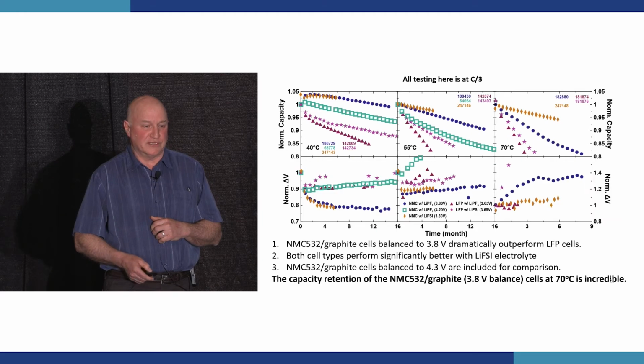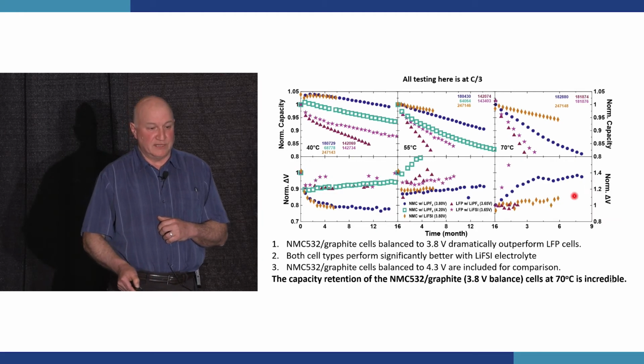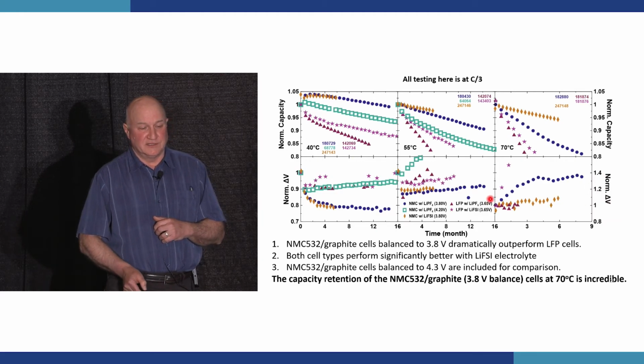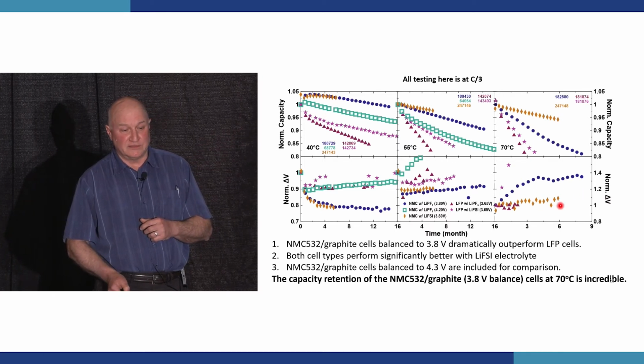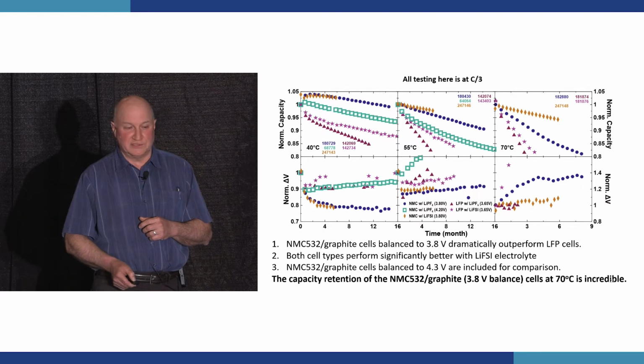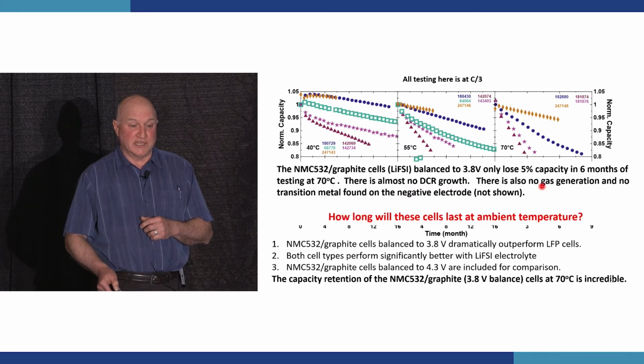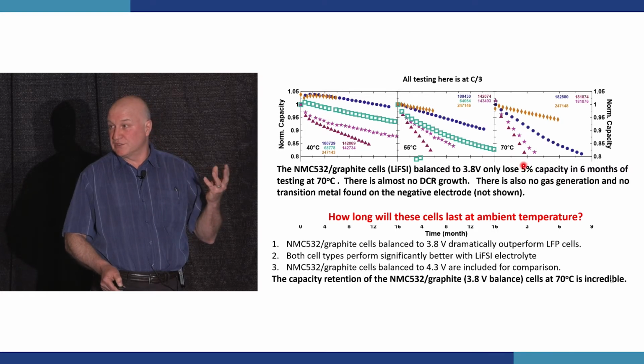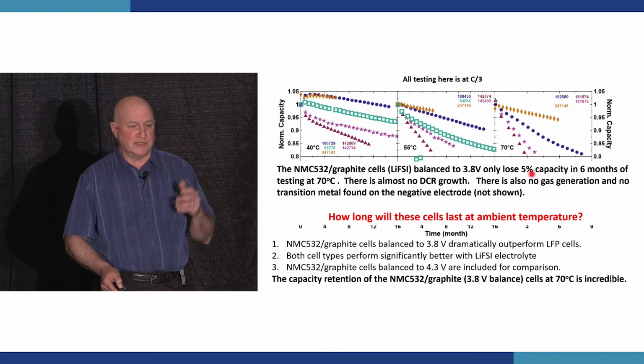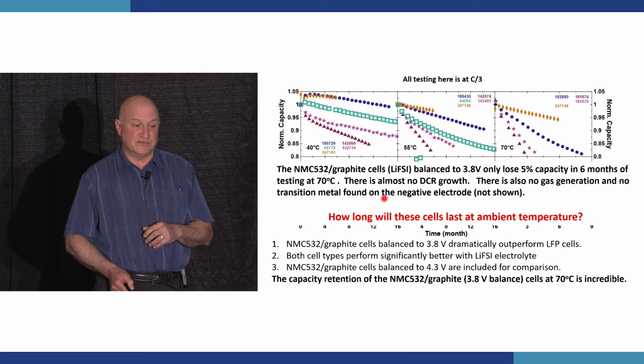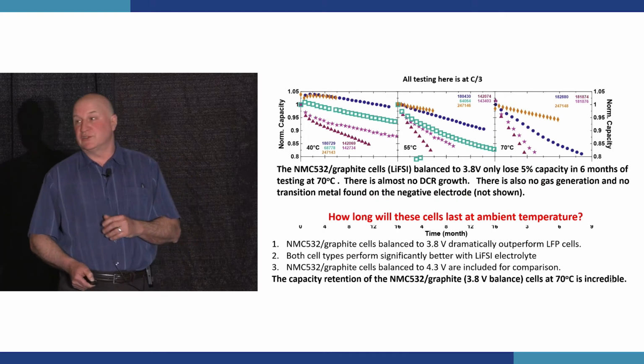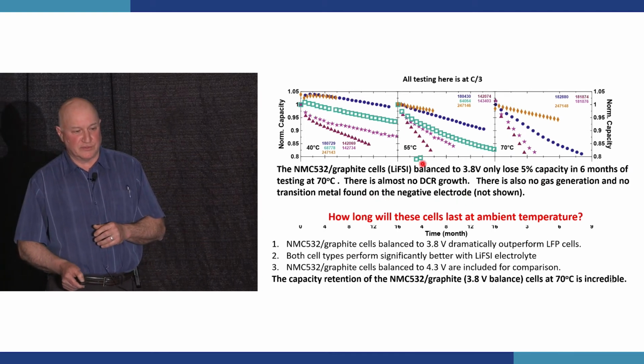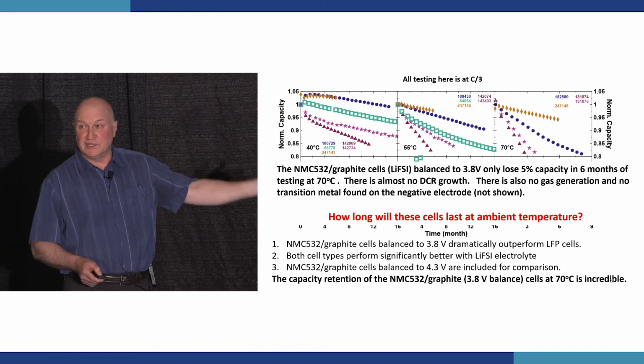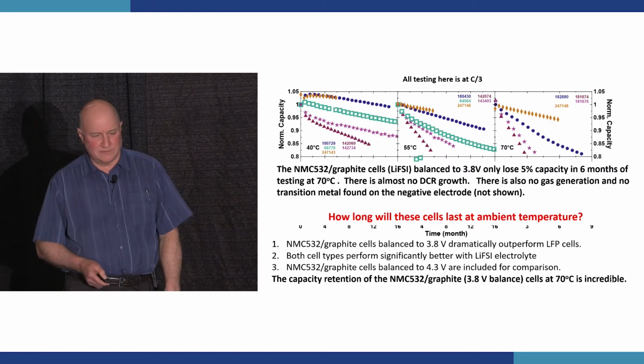There's almost no impedance growth, I forgot to show you that. So down here we're showing the normalized difference between charge and discharge voltage, and it's not growing at all. So there's no impedance growth in these cells at all. There's also no gas generation. In a pouch cell, you can see the gas by the pouch puffing up. And no transition metals found on the negative electrode when you take them apart and look for transition metal dissolution that ends up on the negative side. It's incredible.